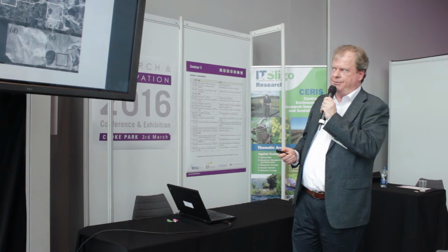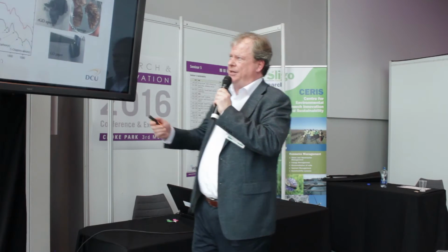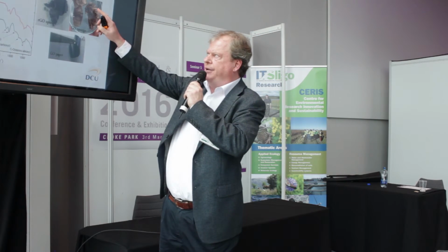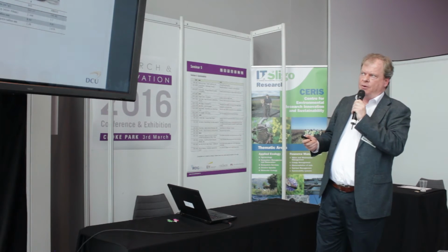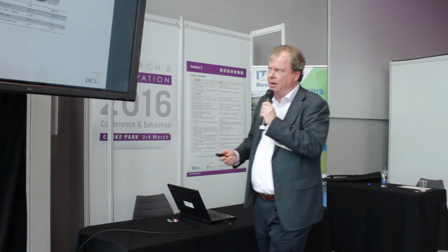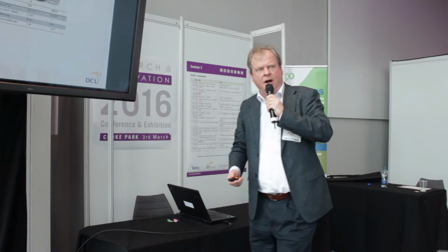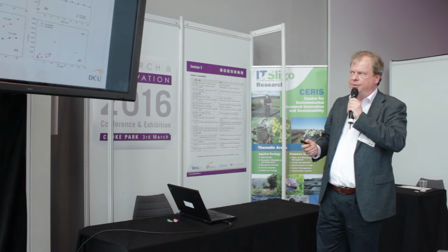Here are just some photographs of what we made over the years. And one of the things we found was more effective: there's a thing called graphene paper. We weren't interested in this. We created, through freeze drying, actual graphene sponges. That way when they hit water, they disperse beautifully. We're looking at some performances of absorption of just graphene, and this is with just methylene blue, so we're getting pretty good absorption, so it is working well, absorptivity. We also have a pretty high surface area with graphene, okay, not as high as activated carbon, but a surface area that's quite sufficient for absorption applications.